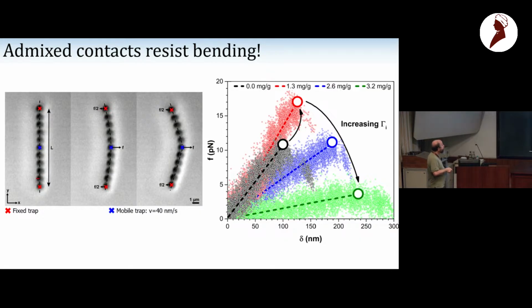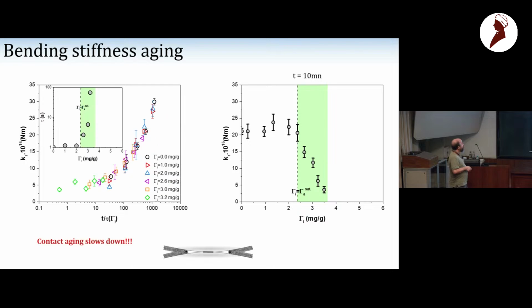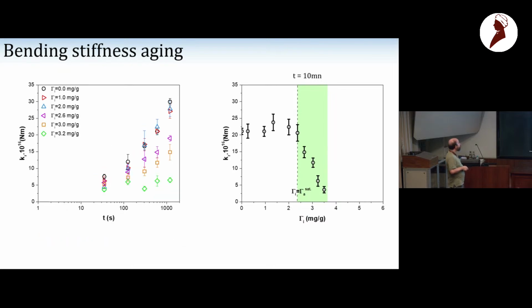So we play the same game. We have much cleaner data because we have a much better optical tweezers now, and so you can see that you continue to have a dependence of the response on polymer, on time. And I wanted to show one thing, which is this. Here we see the bending modulus of contacts, depending on the dosage. And so we see the same thing.